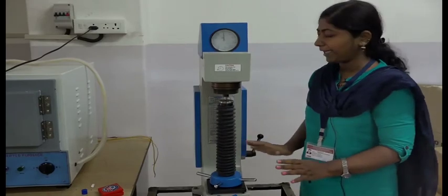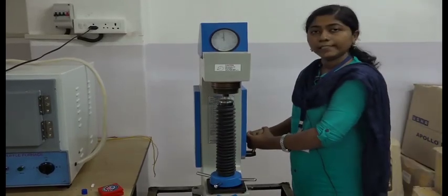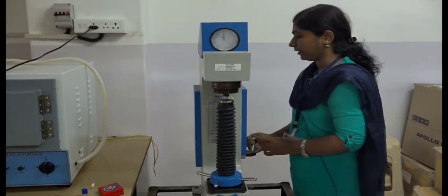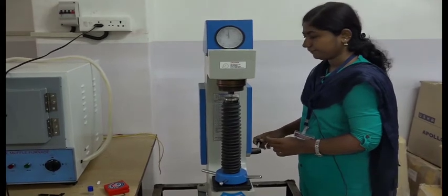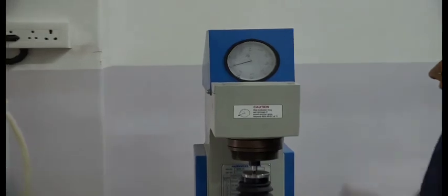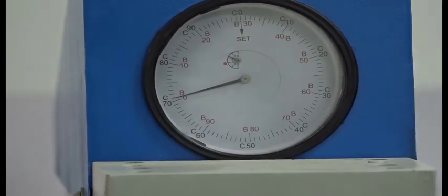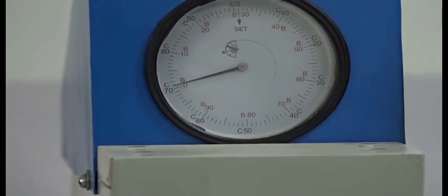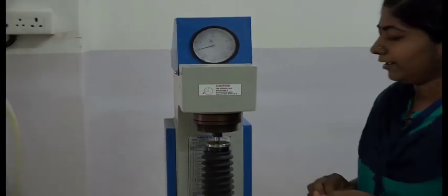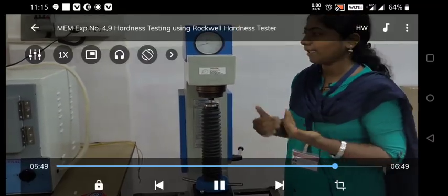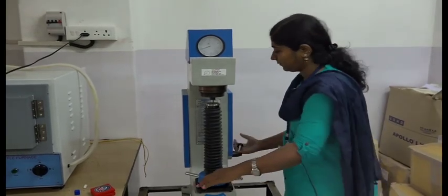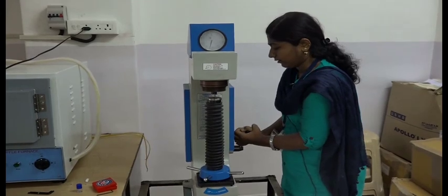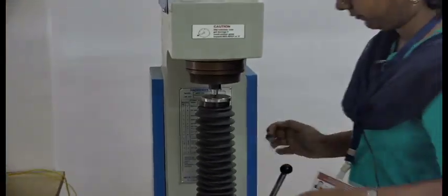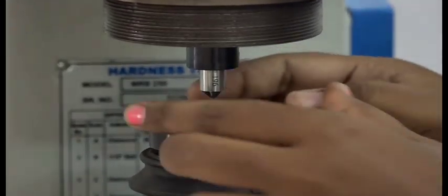The 10 kg minor load is already applied. Now I am applying the lever and giving the load on this specimen. The load is 150 kgf. Now the indicator is stable. The reading is near about 71. Measured on the Rockwell hardness tester, the reading is 71 HRC. Now the machine is unloading, and the specimen is removed. This specimen's hardness is 71 HRC.